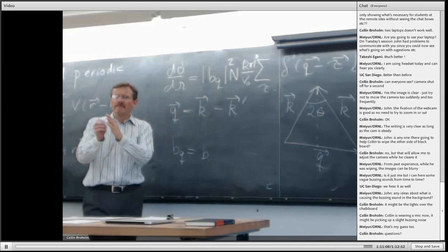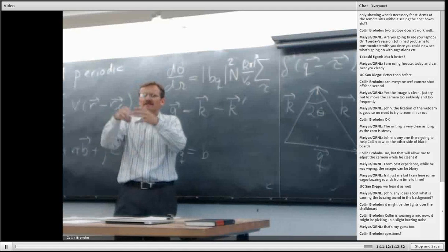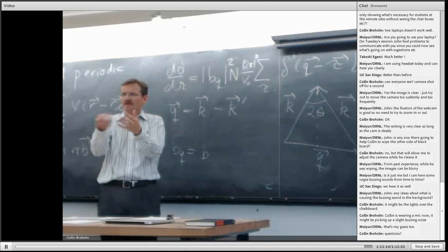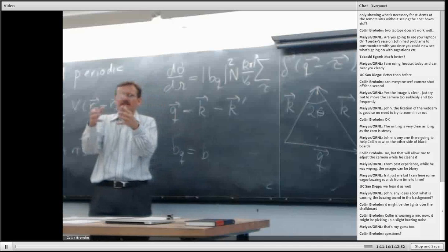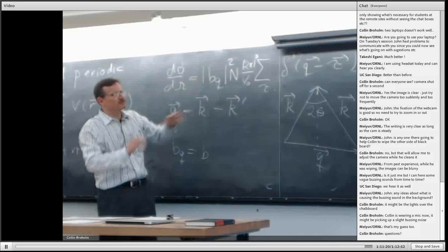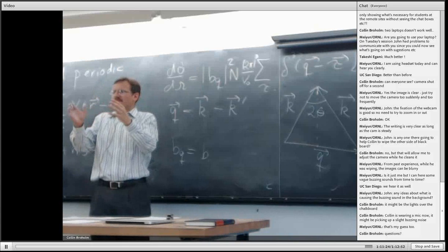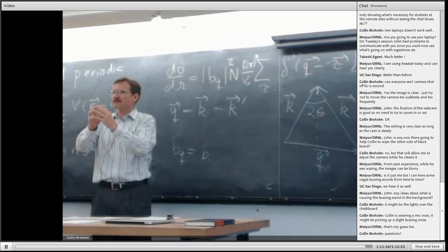But then what happens if I have zero-point motion or thermal motion is that this delta function is actually somewhat spread out because the atom has a finite extent beyond the size of the nucleus. And that will cause this Fourier transform to be the Fourier transform of something that's a little bit larger in real space, which means that it'll actually become smaller in reciprocal space.